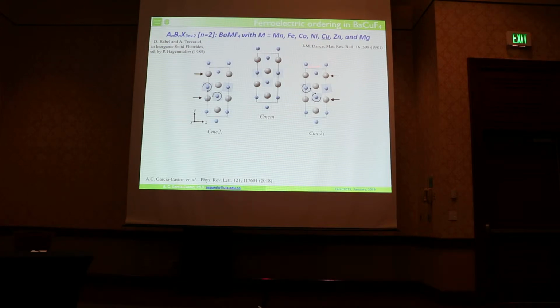What we have in this type of materials, when N is equal to 2, is this type of structural arrangement where we have the octahedra here, and then we have the A site, which in this case is barium. So this is the supposed high symmetry structure, because this structure never reaches the transition as a function of temperature, and is really stable in the polar structure up to 1000 K. So the polarization is coming in this way.